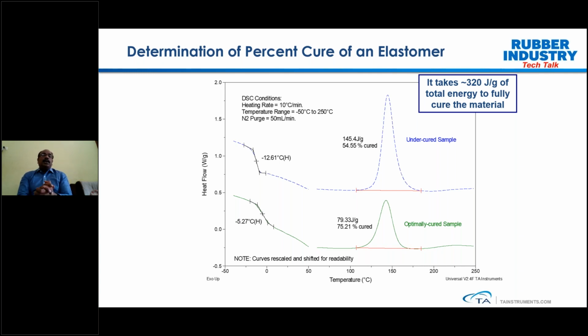When you look at the green compound, clearly the glass transition is showing at minus 5.27 and the exotherm is showing about 79.3. So what you need to do is first take the uncured sample, run the DSC, allow the sample to 100% cure, and quantify how much energy is required. In this case, for this particular sample, 320 joules per gram of energy is required. But what we see here is the optimum cure is 79.3. So if you take the ratio, we can clearly calculate that the green sample is 75% cured.